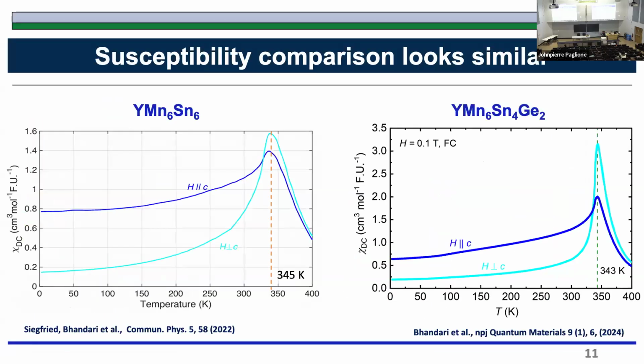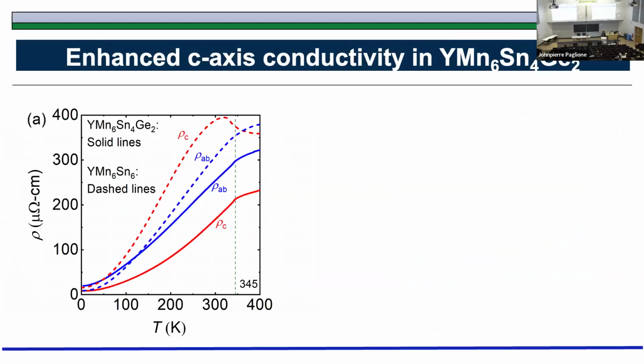We looked into the magnetic susceptibility between the parent compound and then the one with the germanium. It wasn't very different when we look just at the susceptibility, right? They look very similar. The transition temperature barely moves. It was 345 Kelvin, 343 Kelvin, but when we look into the transport properties, we could see a stark contrast between these two.